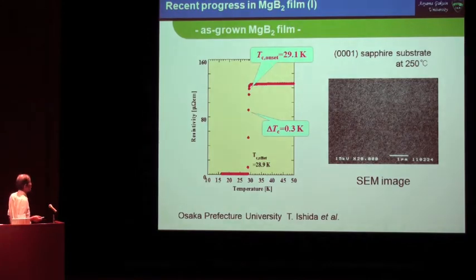Another interesting application is thin film. Recently, these are very, very beautiful SEM images of the magnesium diboride thin film. The substrate is a sapphire substrate, and this is very, very sharp.